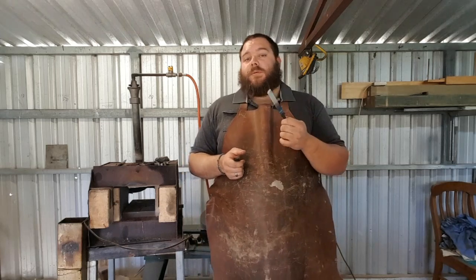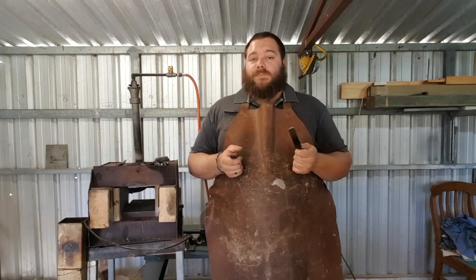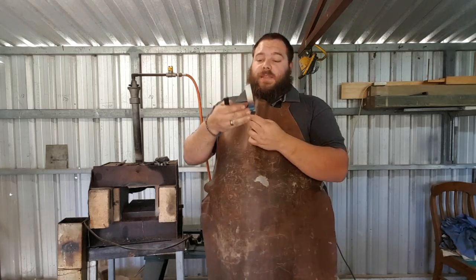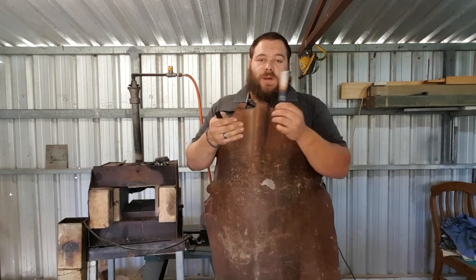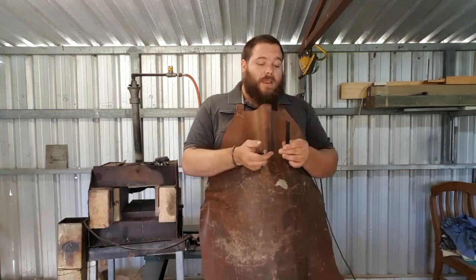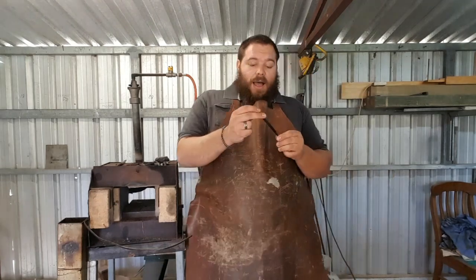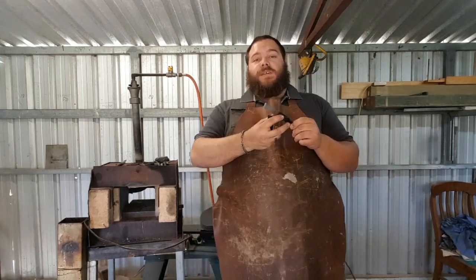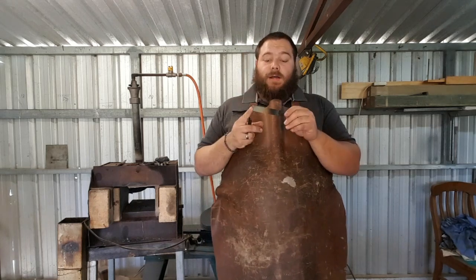So if you're going to do a torch temper, I would recommend doing it at least 3 times and swapping sides between. So if you do it this side first, you get that all to a nice straw color. You flip it, you do the second side, and in between you quench, and then you do the third side again, or the same side again. And that will just guarantee that you've got the temper all the way through the piece, and that's going to give you a better result.